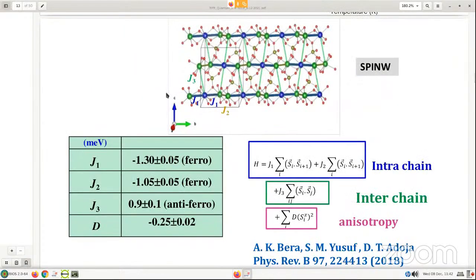And we have determined the exchange constants. That is what I was telling you, that to form the trimer, J1 and J2, taking this kind of Hamiltonian, J1 is the intrachain, meaning along the chain, and J2 is also along the chain, which are responsible for the formation of the trimers. And you see both J1 and J2 are ferromagnetic. That's why you are getting almost a parallel kind of spin configuration. But between two chains, the strength is given by J3, and J3 is antiferromagnetic here, and this strength is almost comparable to the intrachain J1 and J2. So as a result, it is behaving almost like a 3D system, though you do see the chain-like structures, spin trimers, and so on.